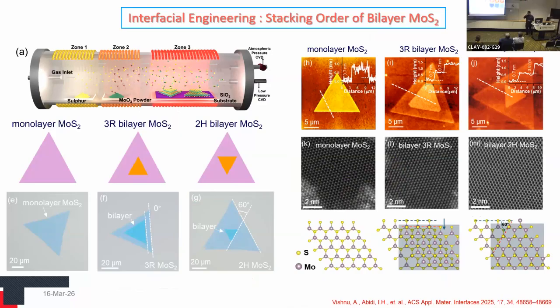So there's another interesting interfacial engineering we can do in the CVD. For example, we have 2 layers of MoS2. We can have different stacking of 2 layers. For example, in the image you can see if you have a monolayer MoS2, one single crystal, and then if you have another layer on top of it, so 2 triangles sitting on top of it at the same angle, it becomes a 0 degree or 3R bilayer, and then we can also have a 60 degree rotation, so it's rotated like 60 degree with 3-fold symmetry. So in that case, you have a 2H bilayer MoS2.